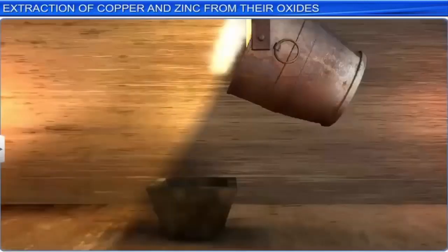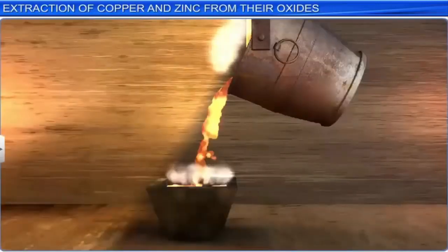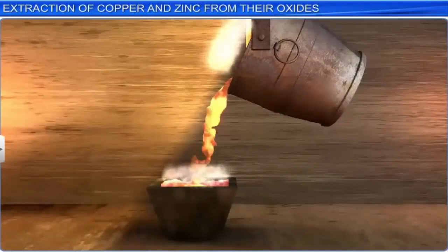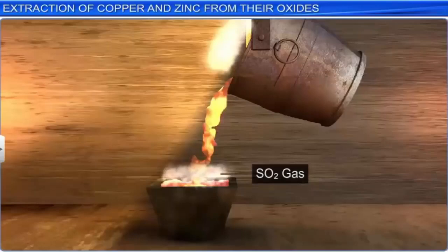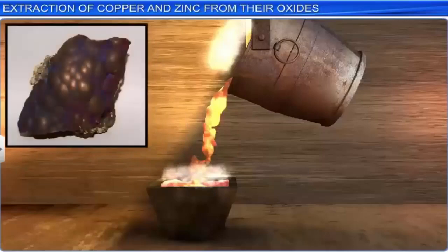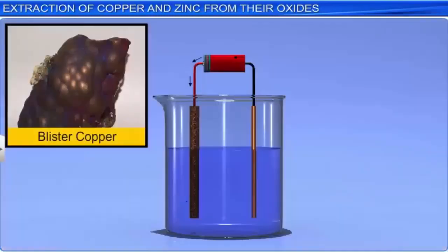This molten copper is poured into molds. When the molten mass is allowed to cool down, SO2 gas escapes. As a consequence, the copper so obtained has a blistered appearance. Hence, the product is called blister copper. Blister copper contains 98% copper and is refined through electrolysis.